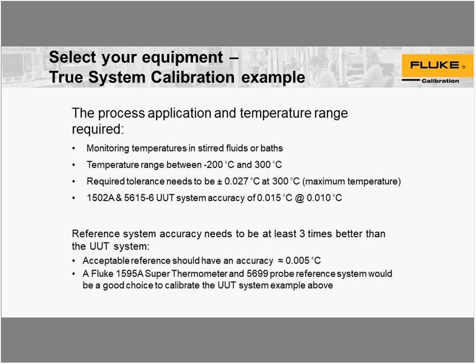And what we wanted for our requirements, our tolerance needs to be 27 millidegrees or less at 300 degrees maximum. So for that, we're looking at a system, a Fluke 1502A with a 5615-6 probe, and it has a system accuracy of approximately 15 millidegrees at 0, and it will be well within our limits at the 300 degree maximum.